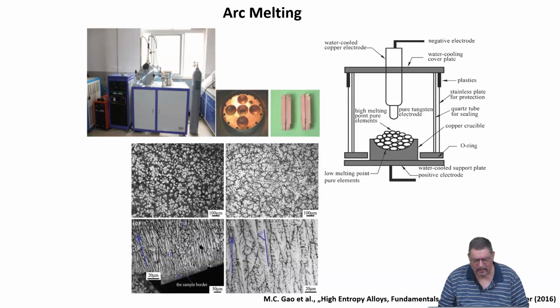Also, as indicated here, you get very complex microstructures because you have a rapid heat flow to the cold copper hearth, which means you have directional solidification, but not in a uniform direction, basically spreading everywhere. And a very rapid heat extraction that favors the formation of a supercooled liquid. And when you have solidification in a supercooled liquid, you know that the solid-liquid interface can become unstable, which means dendrites can form. Then you get a highly directional and fractal crystal phase forming that often doesn't have good properties.